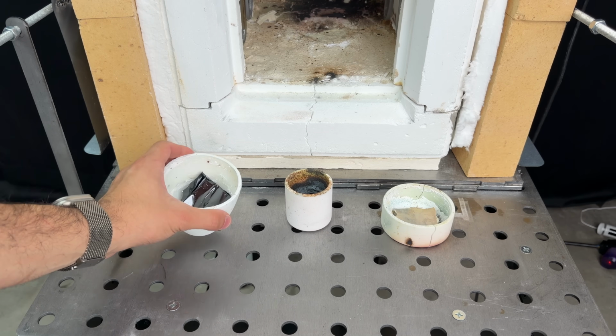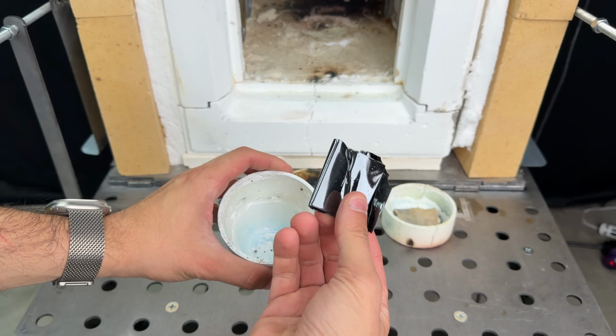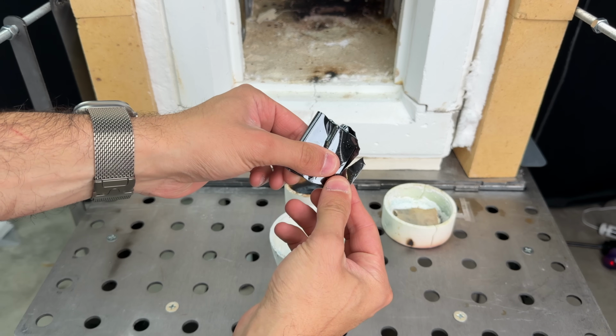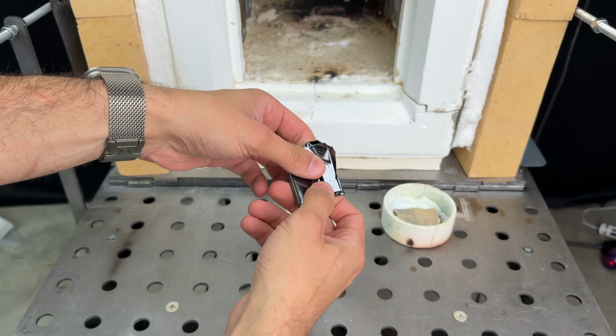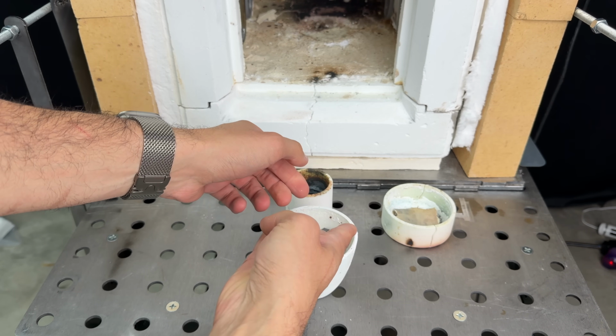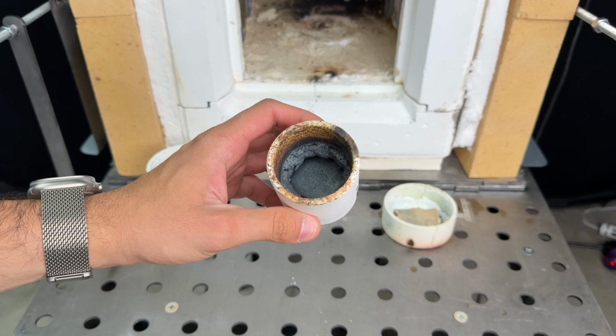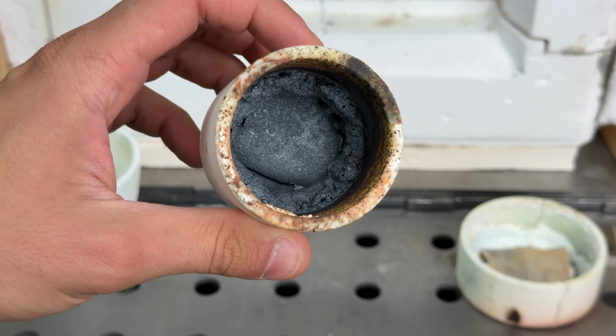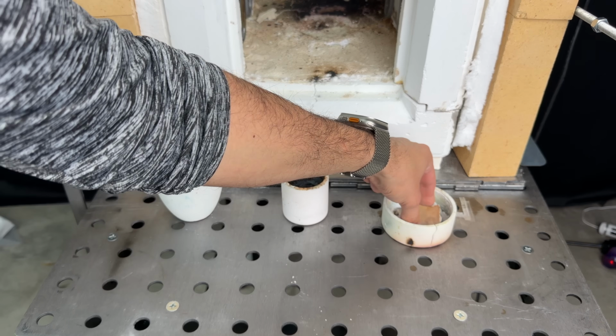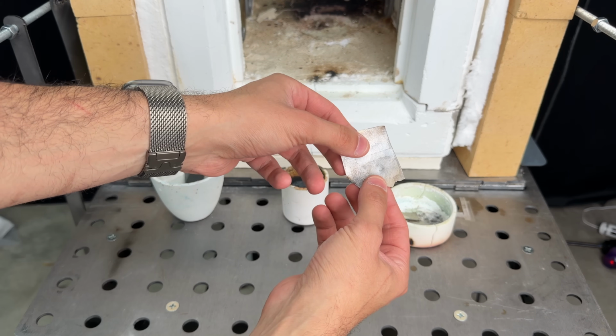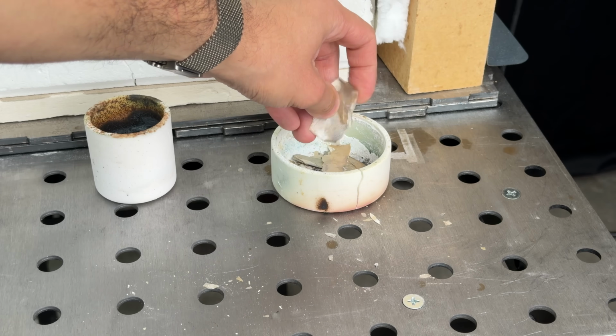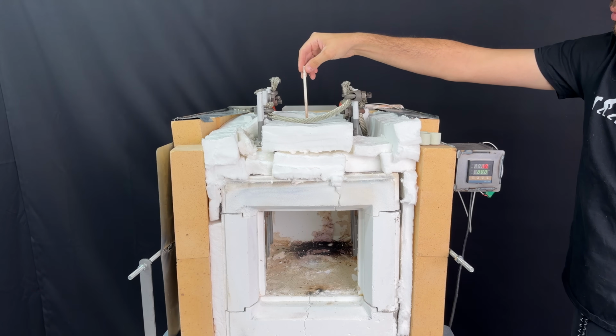When I opened it up, I noticed that the nickel foil was not melted. I believe this is because it was thin, so the oxide layer on the surface prevented drooping. We clearly got hot enough to melt it though, because the iron completely melted, and the titanium, not surprisingly, turned into titanium oxide and has the consistency of Doritos now. So let's start our final run.